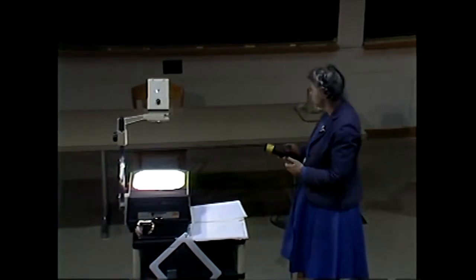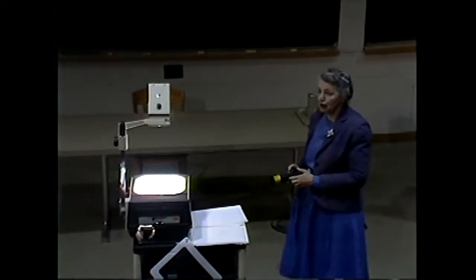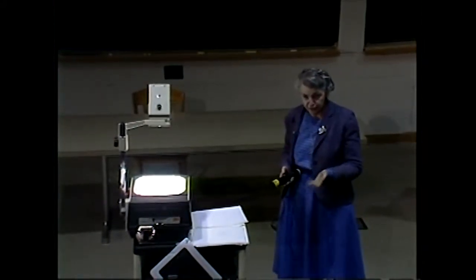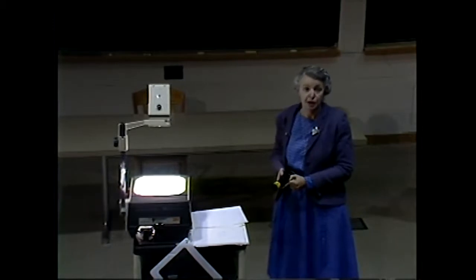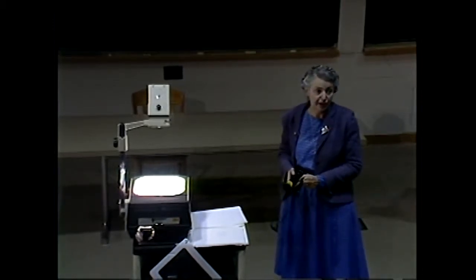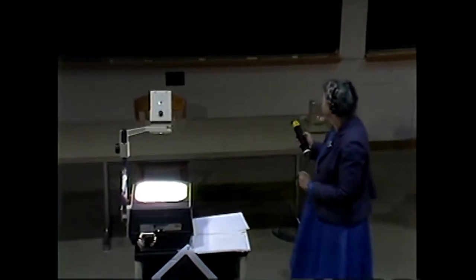Well, the idea of the laser melting, I mentioned last time that graphite is the highest melting temperature material in nature. It melts at about 4450 Kelvin, a very high temperature indeed. So you can't put the graphite in a crucible to melt it, because the crucible will melt before the graphite. So you have to melt the graphite in its own crucible. So here's graphite, and we put a laser beam in, and we're going to make a little puddle of graphite inside a graphite wafer. So here's our laser pulse.